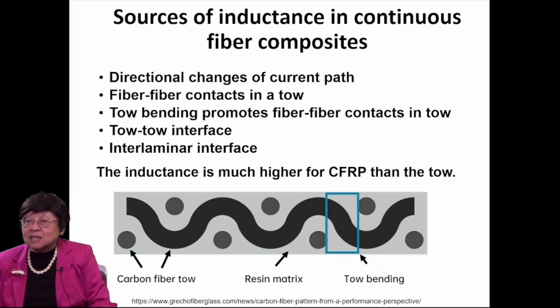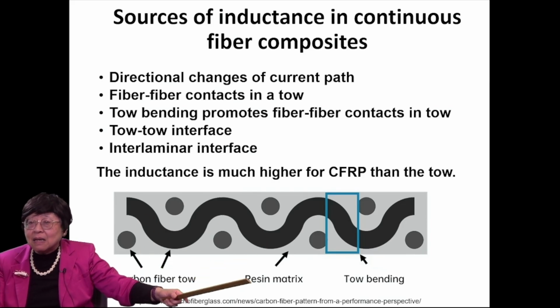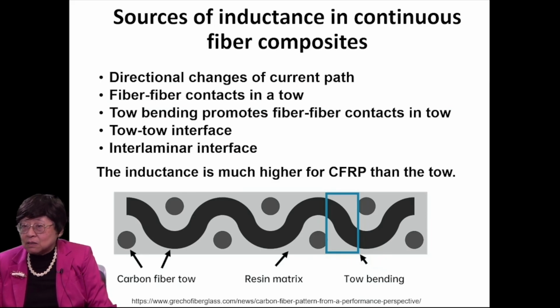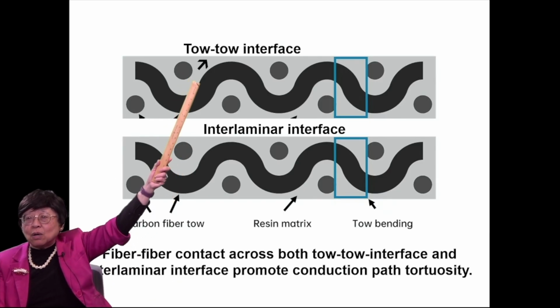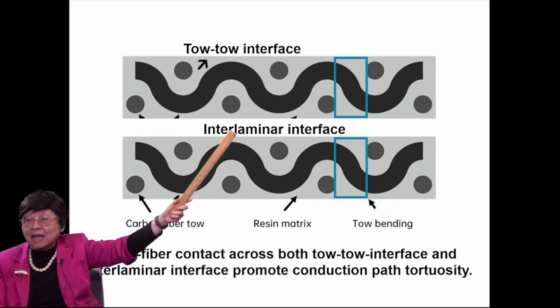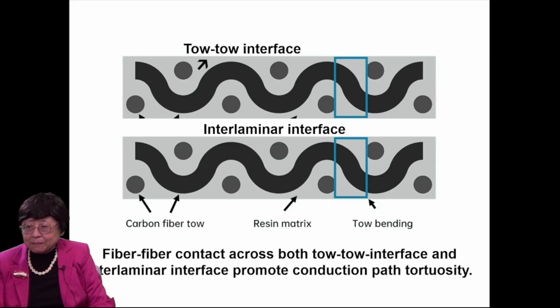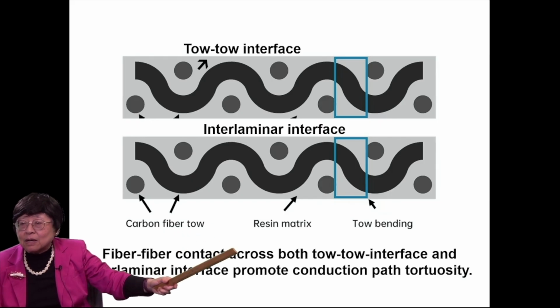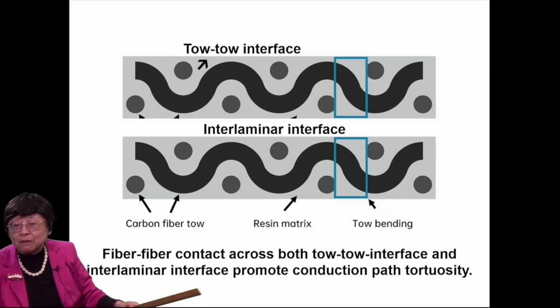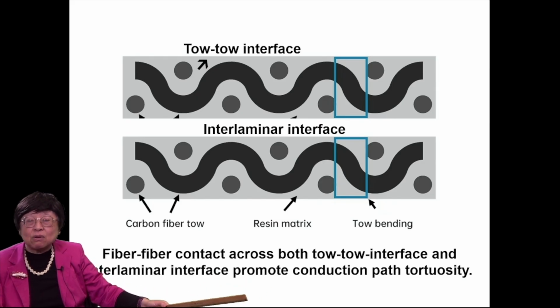The sources of inductance in continuous fiber composites include these: directional changes of the current path, that is the tortuosity of the current path, the fiber-fiber contacts in a tow, the tow bending, as illustrated here, promoting fiber-fiber contacts in the tow, also the tow-tow interface and the interlaminar interface. As a result, the inductance is much higher for CFRP than the tow. And this is what I mean by the tow-tow interface. And here is the interlaminar interface between the two laminae. The fiber-fiber contact across both tow-tow interface and interlaminar interface promote conduction path tortuosity.